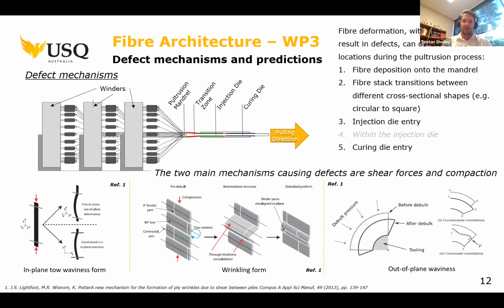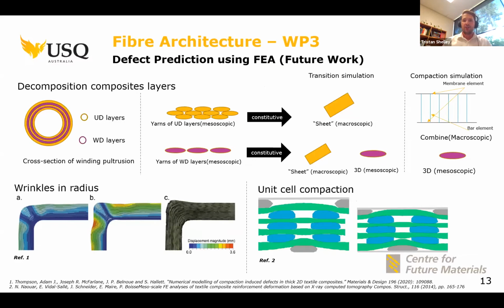So there's 2 main mechanisms that cause the defects. These are the shear forces between subsequent layers and also the compaction of the fiber stack at various stages of the pultrusion process. So using finite element analysis to predict these, we need to find some way, without the model being too cumbersome or unable to run within a realistic time frame, we need to find ways of representing individual tows or individual rovings in an FEA model, such as a membrane or a shell element or something similar to that.